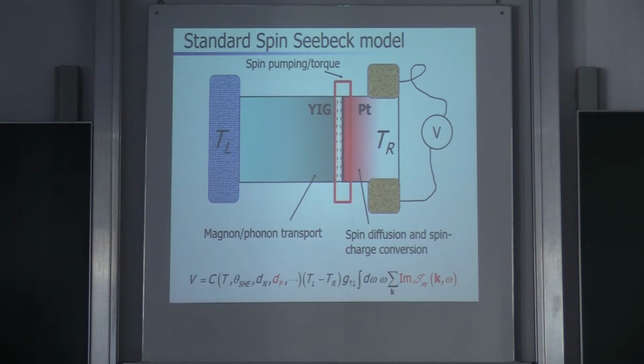Finally, there is the fact that the magnons, if they are depleted here at this point, have to be filled from the bulk. So there's also spin current generation and spin-Seebeck effect from the bulk itself. And all these processes are important to describe what is happening here. Now, I will not discuss too much about what is happening here exactly, but the point is that if the temperature gradient in the bulk is larger than the temperature gradient which you have at the interface, this process, what happens here in the bulk, is very important.